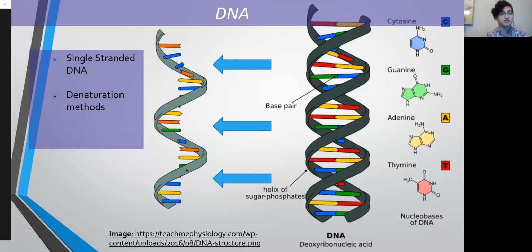This can be done with various methods. Three of the most common ones are chemical melting, where we introduce an additional chemical, thermal melting, where we change the temperature, or the lowering of the salt KCl concentration of the DNA mixture. By doing this, we're able to stabilize the single-stranded DNA and use it for DNA translocation. Important things to note are that the diameter of the single-stranded DNA is approximately 1.1–1.3 nanometers, while the distance between each individual pair of bases is about 0.33 nanometers.